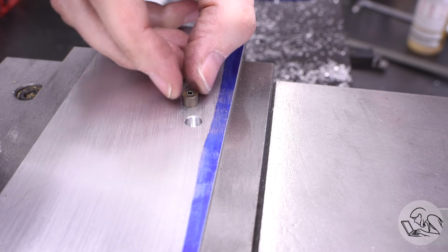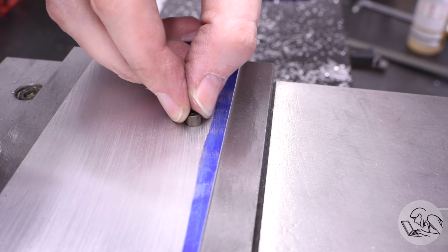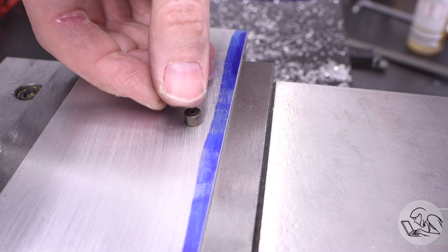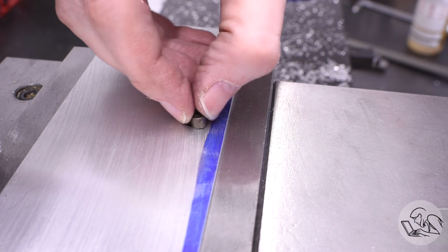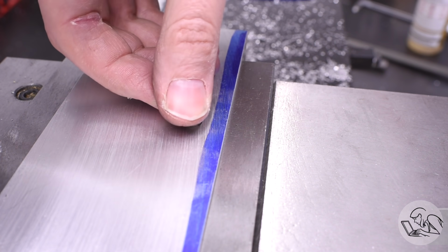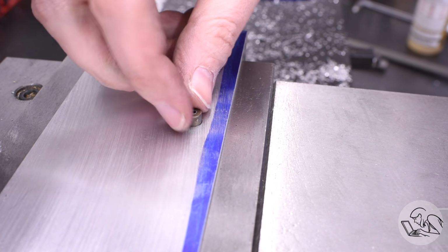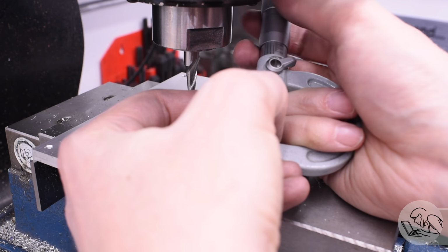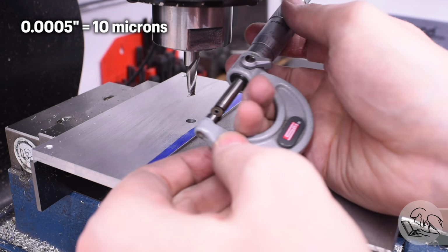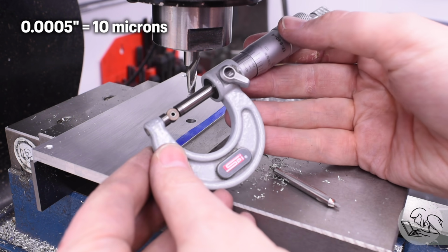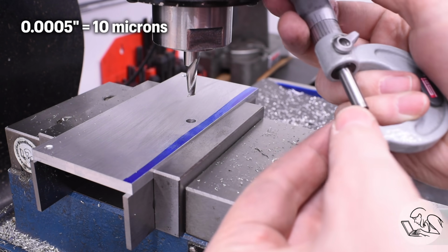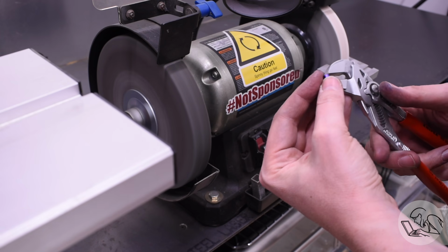Moment of truth, let's see if my die fits in the hole. The answer is, no it doesn't. And well, this was probably to be expected. The hole is on size, but the die is actually slightly oversized. When I made this die, it was about half a thou under nominal, which should have made a very nice sliding fit into that hole. But since heat treating it, it's now about half a thou oversized. So it expanded a little bit in the heat treat, which is typical.